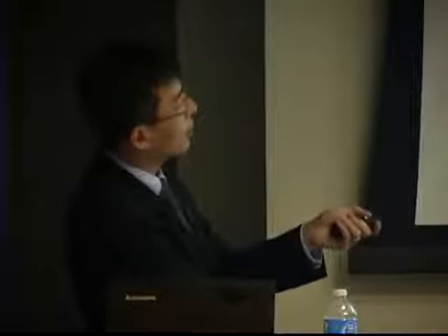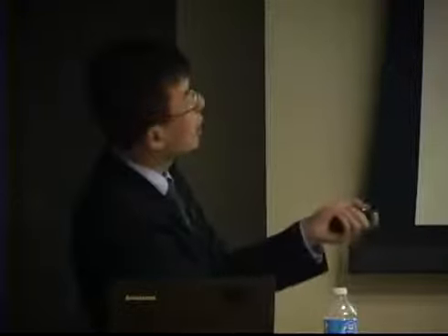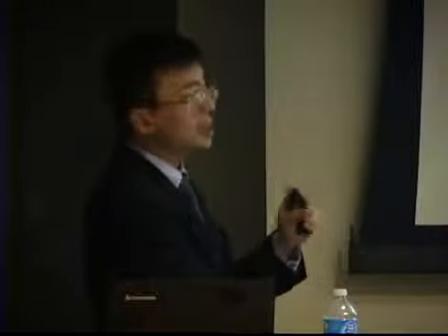So you see, at the shorter wavelength regime, semiconductor is a very good absorber. Once light comes in, it gets absorbed right away. So from the simulation data, this white, big contrast color means there is light. Once it becomes white, it means all the light has been absorbed, right? So for the short wavelength regime, once light gets coupled in, it gets absorbed right away. So the difference you see here in the short wavelength regime is due to reflections. That means even when the cone becomes slightly like a dome shape, they still maintain good anti-reflection properties.